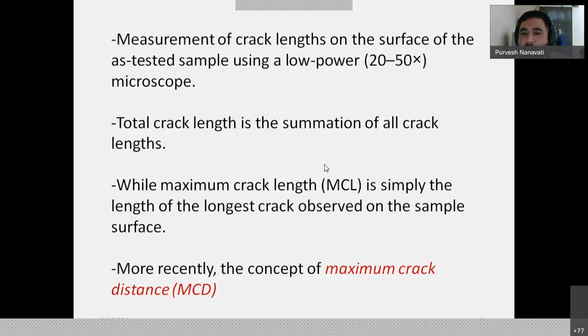So previously, people were measuring the maximum crack length, then they were making a summation of the different crack lengths. Now they have come to a conclusion by years of experimentation that the most accurate is to measure the maximum crack distance, MCD, the distance through which the crack has propagated, right? MCD. Okay.